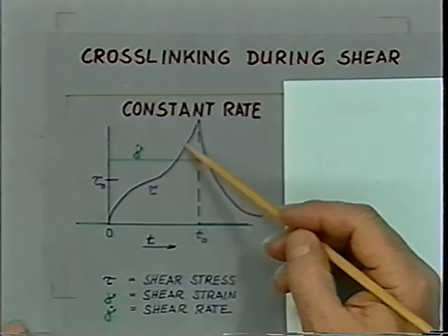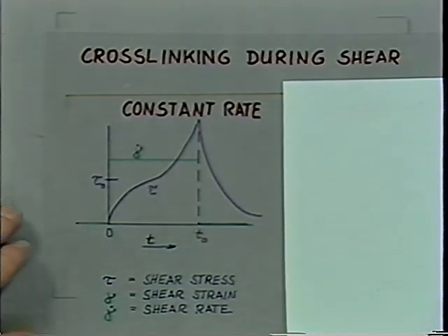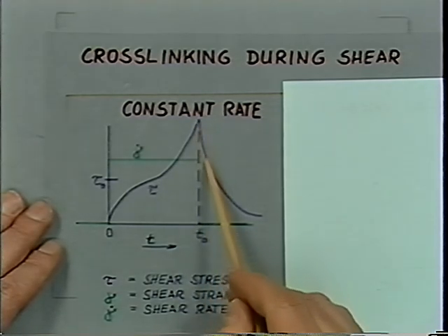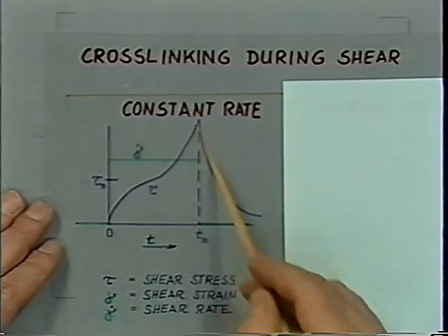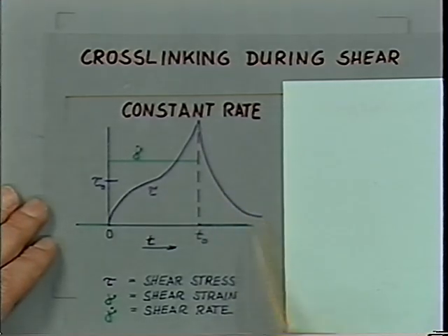So there's a rapid growth of the stress, and when we stop the flow, some of the strain will recover, because it's an elastic body. It wouldn't recover to 0, so what I did here in this graph might be overdoing it.